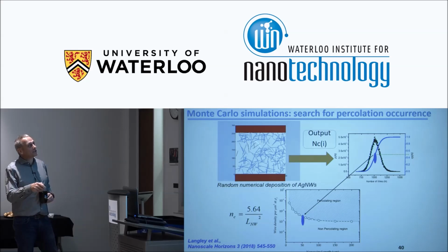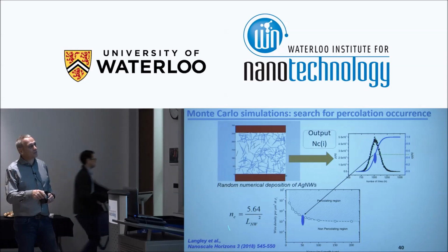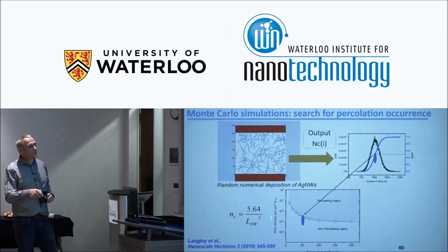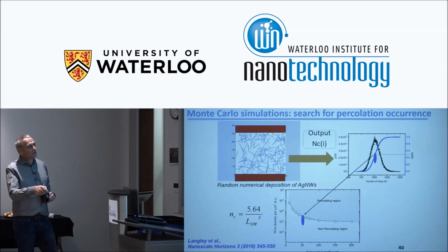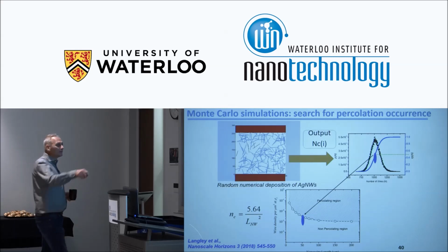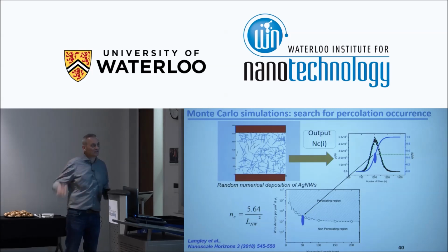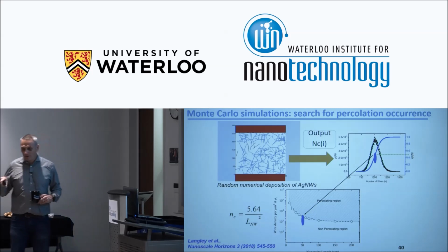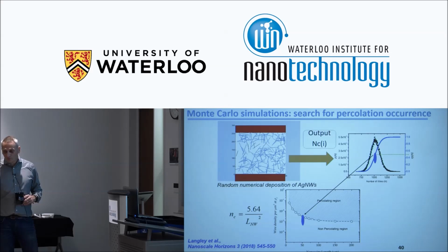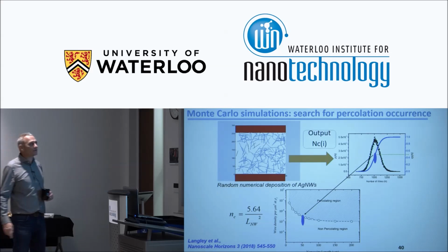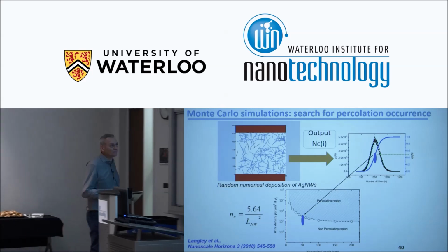And we can for sure change the length, and we can observe this formula. Okay, this is well known. It has been done several times in literature, so there's nothing new about that. And for sure, if you plot the log of NC versus the length, we have something like this. So this is the non-percolative region and the percolative region. Okay. But in this paper, we didn't do that only because it was already well known. But we try to quantify the imperfection in the real world, and to assess what is the influence on the physical properties of this network.